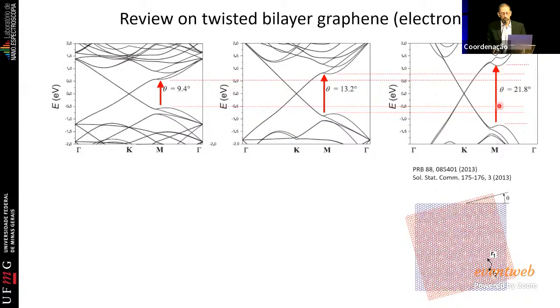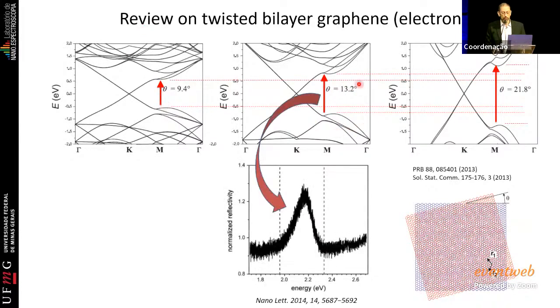And what we notice is that, again, the angle controls this gap. And if you do, for example, an optical absorption on graphene, you have a peak in the absorption and in the reflection, and the energy of this peak will change when you rotate the angle. And it changes quite substantially. It changes from zero, that is the zero-gap semiconductor, up to almost 3 or 4 eV, okay?